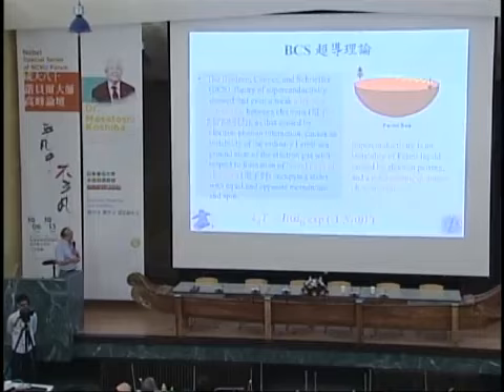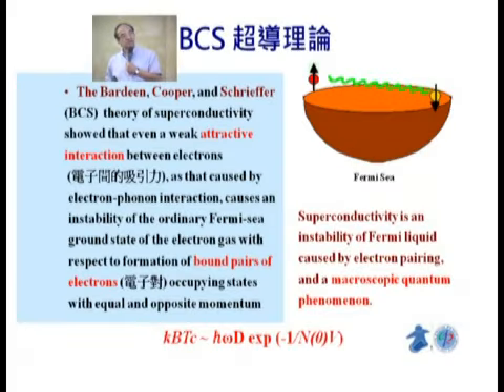there was a very important relation that physicists or chemists can follow in terms of understanding the fundamentals of superconductivity, and also it can become a good guideline in the search for superconductors, particularly related to some of the fundamental parameters, like the superconducting transition temperature, the Tc. It can be related to some kind of energy. And here, without going into detail, this is the electron phonon, the lattice vibration frequency, and those are the parameters of the material related to the density of states of the electron and the electron phonon interaction strength. If you look at this mathematical relation, you can tell that if we want to have a higher Tc, the temperature higher and higher, you want to have this number large.